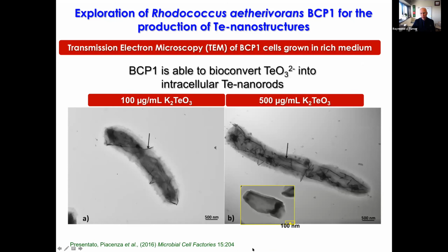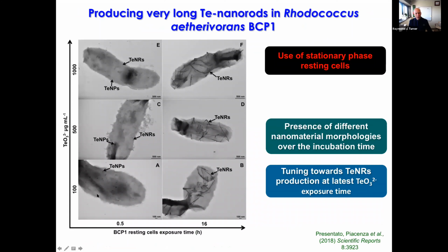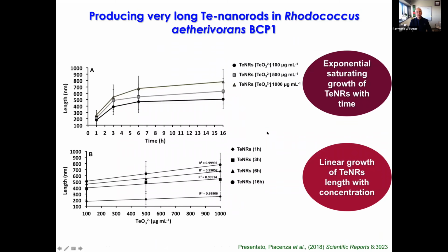So here we'll show you some of the results we were able to get, and some first tries of making nanorods with this organism. We're starting to get quite nice long nanorods. They're being made inside the bacteria. We play with concentration and time, and we use stationary phase resting cells that are producing a lot of the biosurfactant. When they're early in their growth, they don't produce much biosurfactant, and we're getting nanoparticles kind of hidden around in this.